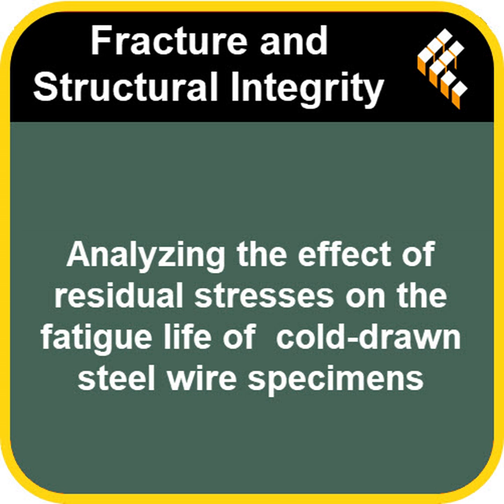Okay. Any challenges in the testing? They did mention one thing. Adjusting the machine's control system, the PID feedback, was tricky for these wires because they're quite flexible. So that meant they couldn't run the fatigue tests super fast. They were limited to about 10 cycles per second, 10 hertz. Still pretty fast, but maybe slower than they'd ideally want for quick experiments.